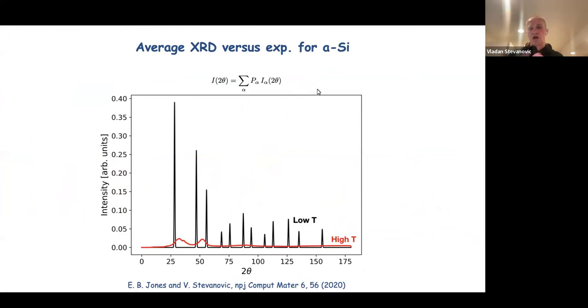So this is just an equation for how one would average modeled X-ray diffraction patterns. Basically, we take these 10,000 or so, 9,000-something local minima that we identified. We calculate an X-ray diffraction pattern for each one, and then just average them according to the rules of classical statistical mechanics. And at low temperature, of course, it is the ground state that dominates. So you see the crystalline features of diamond silicon, so nothing unexpected there.